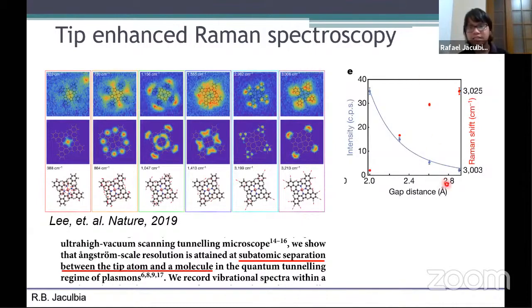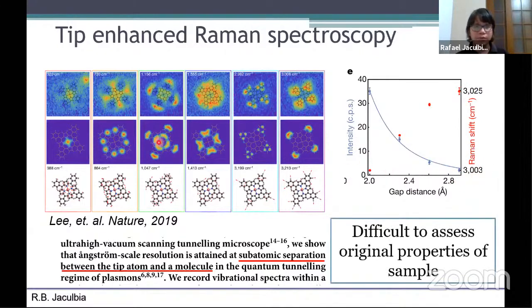And although this has shown good spatial resolution and very strong Raman signal, in fact, the Raman peaks are affected. So here is a gap distance dependence. This is the separation between the tip and the molecule, and red dots are the Raman signals. As you can see, when the tip is far, for example, this mode has 3025 wave numbers. And then as they approach to 2 angstroms, so this data were taken at 2 angstroms separation, the 3025 mode actually became a 3003 mode. So this means that with this technique, although you can get a very good spatial resolution and very strong signal, it's difficult to assess the original properties of the molecule because the measurement itself changes the molecule.